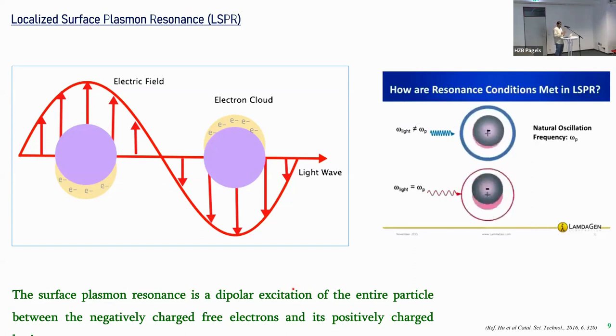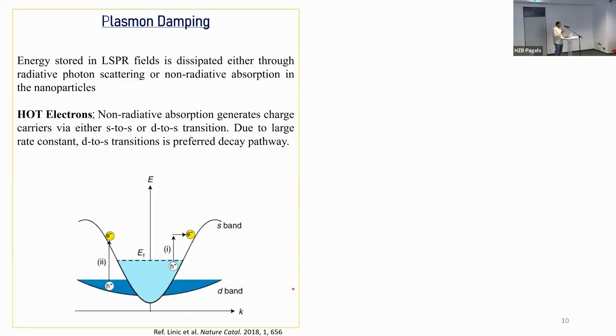So that's the LSPR. Now if I take a 10 nanometer gold particle, the resonance will be around 550 nanometers, so I can get a 550 nanometer wavelength harvested by that nanoparticle. If I want to change the wavelength of absorption, I can change the size of the particle and tune the lambda max. However, a more exciting thing happens after the LSPR, once that resonance is broken: that entire energy is now damped onto the surface. Right? So whatever sun energy is absorbed by the material is damped onto the surface.